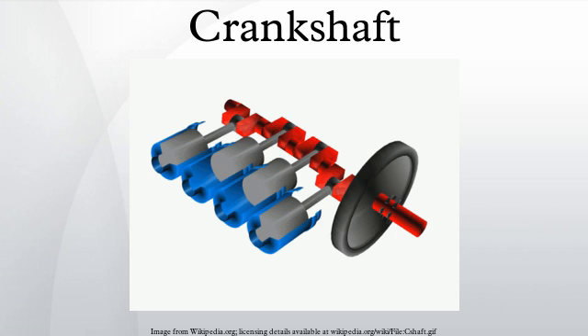Forging and casting. Crankshafts can be forged from a steel bar usually through roll forging or cast in ductile iron. Today more and more manufacturers tend to favor the use of forged crankshafts due to their lighter weight, more compact dimensions, and better inherent dampening. With forged crankshafts, vanadium micro-alloy steels are mostly used as these steels can be air-cooled after reaching high strengths without additional heat treatment, with exception to the surface hardening of the bearing surfaces. The low alloy content also makes the material cheaper than high alloy steels. Carbon steels are also used, but these require additional heat treatment to reach the desired properties. Iron crankshafts are today mostly found in cheaper production engines where the loads are lower. Some engines also use cast iron crankshafts for low-output versions while the more expensive high-output version use forged steel.